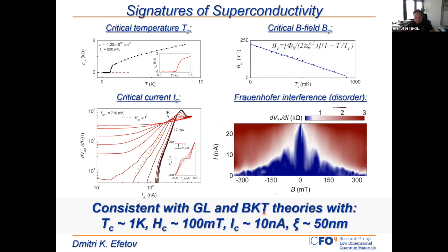And I think so far, the smoking gun evidence, which leaves little room for alternative interpretations, is that in most devices we observe Fraunhofer interference patterns. So we have really coherent Josephson junction coupling in the device if there's a weak link created somewhere that interrupts the superconductor. And from these measurements, actually from magnetic field measurements, we can also extract the coherence length of the superconductor, which is usually on the order of 50 nanometers. So it's on the order of several lattice constants of the Moiré.